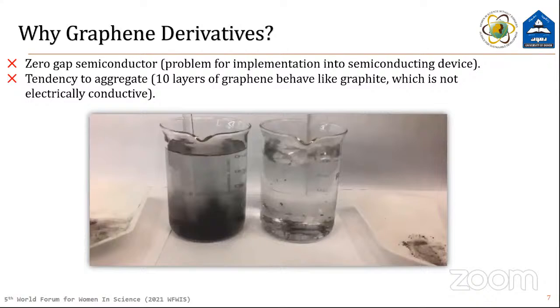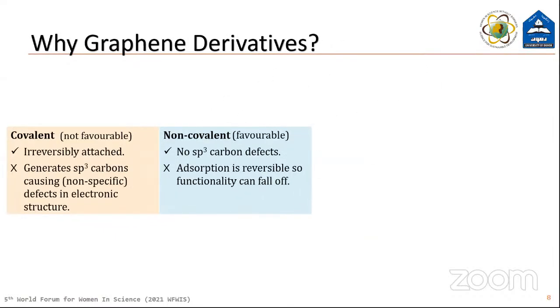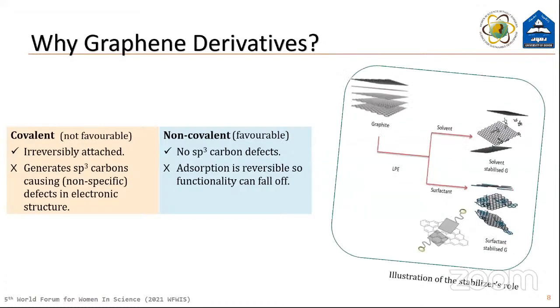more than 10 layers of graphene behave like graphite. However, this can be tuned by functionalization. The reaggregation and restacking of graphene layers occurs as a result of the strong interlayer van der Waals forces, with a view to reduce surface free energy. So the graphene surface must be altered to overcome this issue, and this can be achieved either by functionalization covalently, which is not favorable because it disturbs the aromatic system within the basal plane, influencing the conductivity of graphene, or by stabilization non-covalently, or dispersion of graphene in a particular solvent, as shown schematically in this figure.